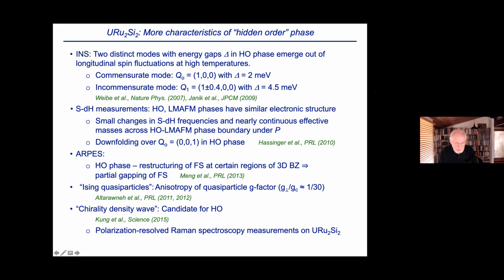Okay, so a lot of ARPES has been done on the hidden order phase, and there one finds a restructuring of the Fermi surface at certain regions of the 3D Brillouin zone boundary, leading to this partial gapping of the Fermi surface. And then another interesting feature is what are referred to as Ising quasiparticles. There's anisotropy of the quasiparticle g factor, a huge anisotropy. And then also one of the more intriguing candidates for the hidden order phase is what's called a chirality density wave. And this comes from polarization resolved Raman spectroscopy measurements made by Kung and coworkers. And if I have time, I'll come back to that. But I'm not going as efficiently as I had intended, so I may not get there.